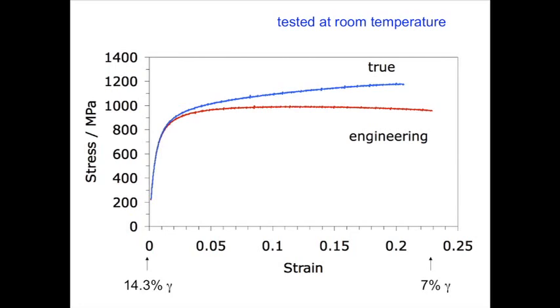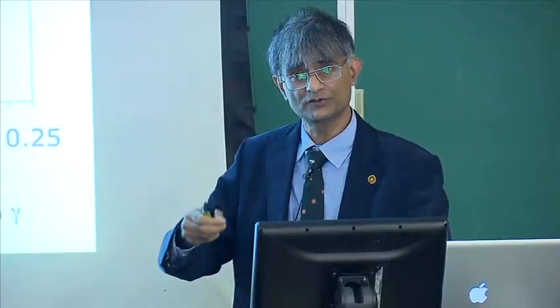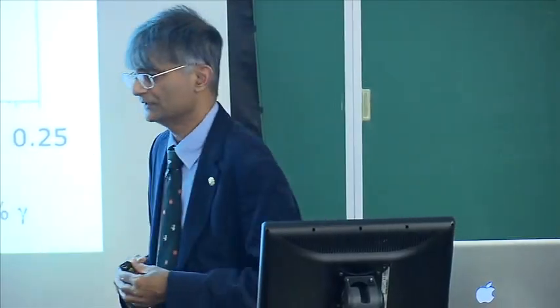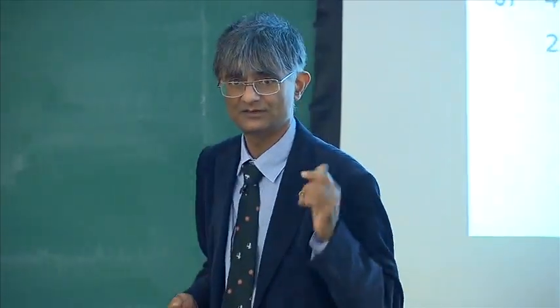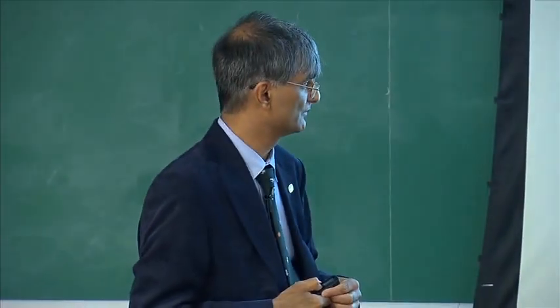And we seem to have almost the right amount of work hardening. That means, if you have work hardening which is very steep, it gets too strong, and then it will break. Okay? You want a curve which is something like this, where the austenite transforms gently. Now, to prove that it's the transformation of the austenite that is helping us get this elongation, we did this